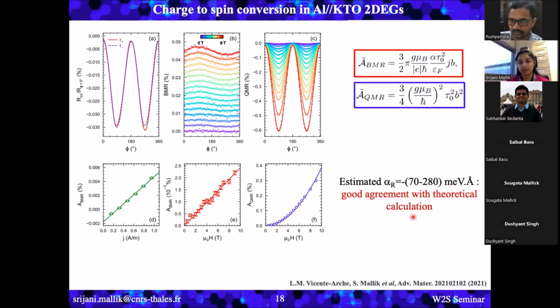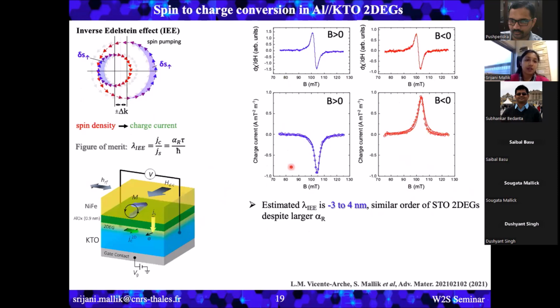So of course we wanted to study the reciprocal effect, that's the spin to charge conversion. And for spin to charge conversion, we need to inject a spin current. And to do so, we took advantage of spin pumping measurements. So we deposited like 20 nanometer of permalloy layer on top of the aluminium oxide. And then we performed FMR measurements.